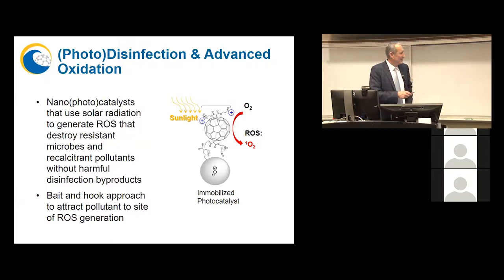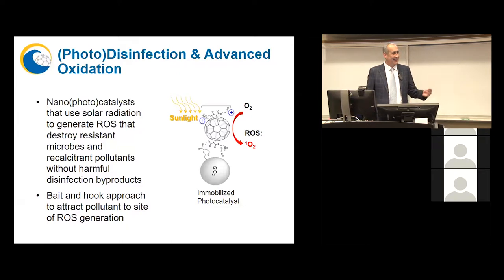Well, we advocate something that we call the bait, hook, and destroy approach, where you attract the target near sites of photocatalytic ROS generation so that the oxidizing species can be used more efficiently. In this case, using the Bingel reaction, we attach this chain with an amino group that is positively charged because bacteria and viruses are negatively charged. So we're using electrostatic attraction as our hook to destroy and kill these germs.